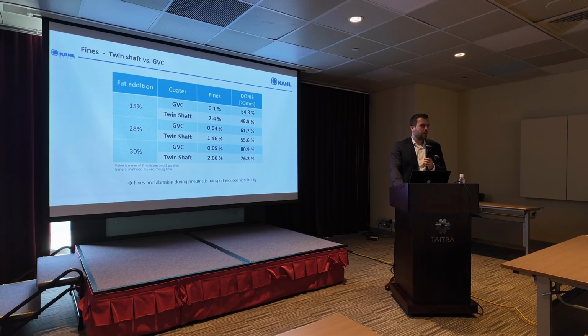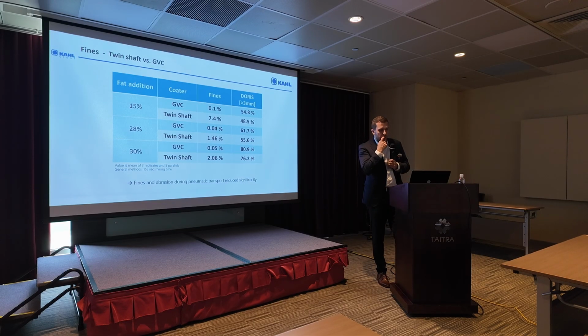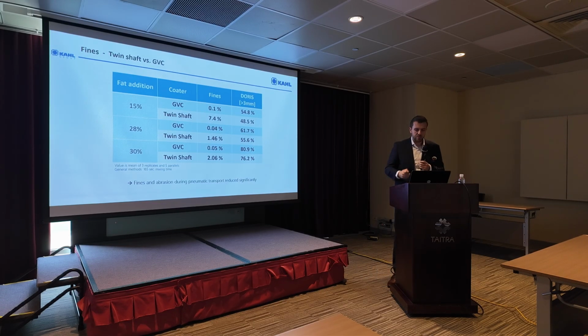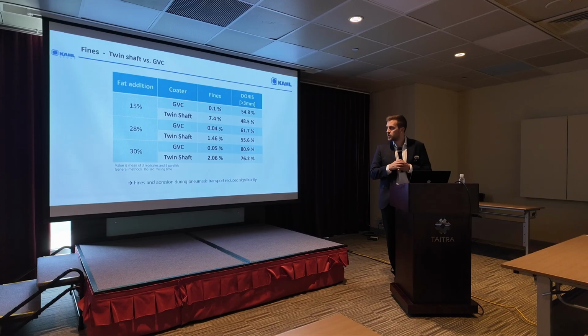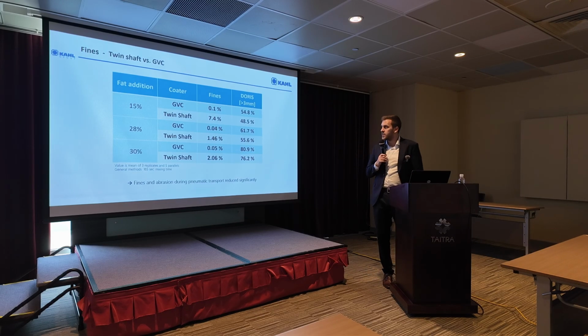Of course, now I talk about gentle, so what does that mean? We did some trials with the institute in Norway and compared our new coater, the gentle vacuum coater, to the twin shaft mixer. And we tested this for different fat additions.